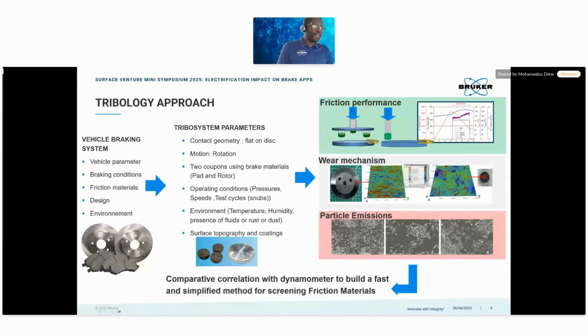And with this, we can characterize the friction performance and the wear, using surface topography analysis of the surface before and after, and also on a pin. The size of the samples will allow us to do characterizations, such as chemical characterization to get access to the chemistry or structure modification due to the friction, and also other characterizations, like nano indentation, for example, to get access to parameters that change on the surface and can explain the stability or instability of the friction behavior of the system.